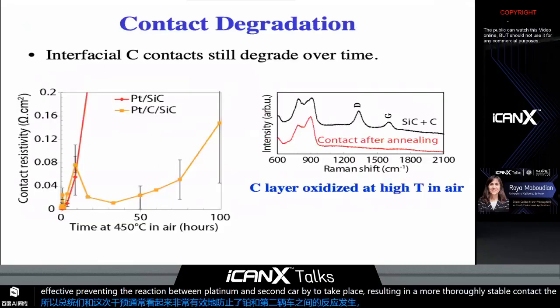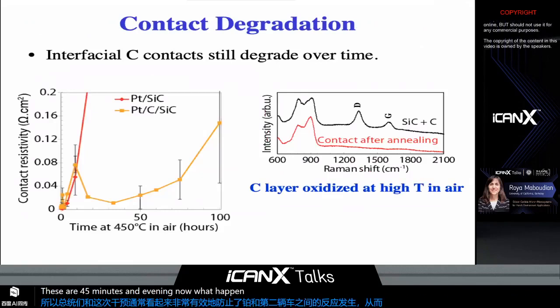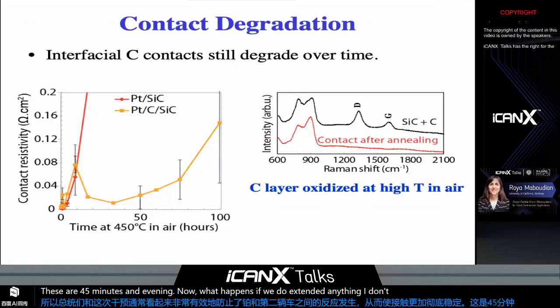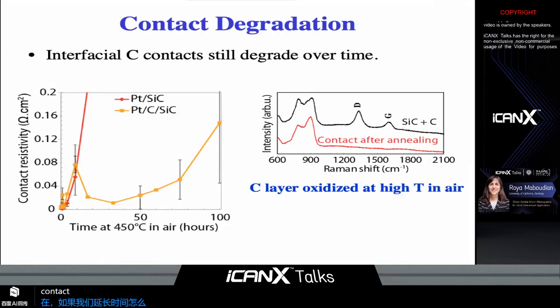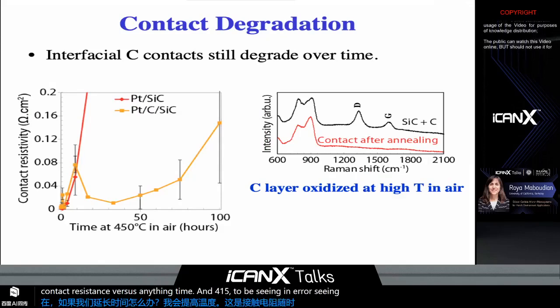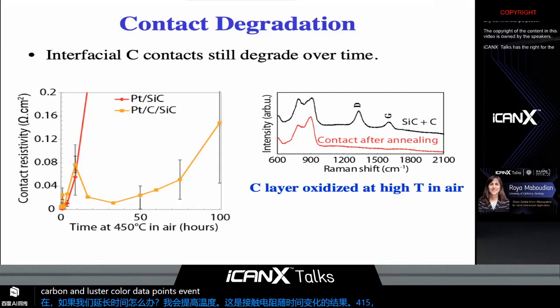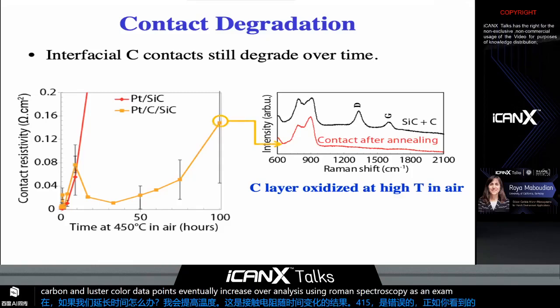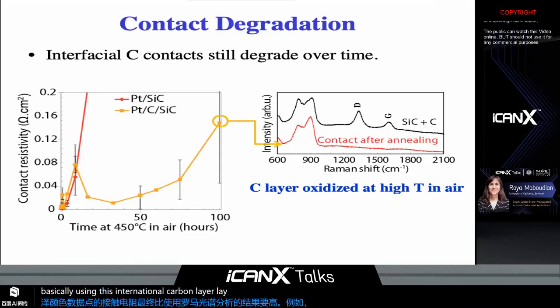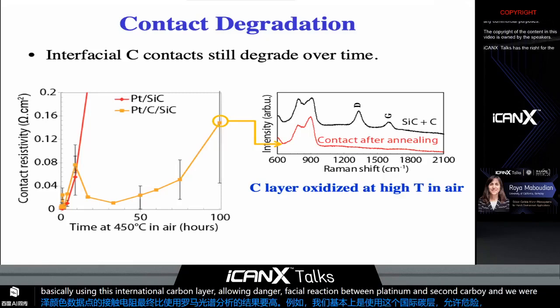These are for 5-minute annealing. Now, what happens if we do extended annealing at elevated temperatures? Here are the results of contact resistivity versus annealing time at 450 degrees C in air. As you see, the contact resistance of the sample with interfacial carbon, the mustard color data points, eventually increases. Our analysis using Raman spectroscopy, as an example, indicates that we are basically losing this interfacial carbon layer, allowing the interfacial reaction between platinum and silicon carbide that we were trying to prevent to occur.